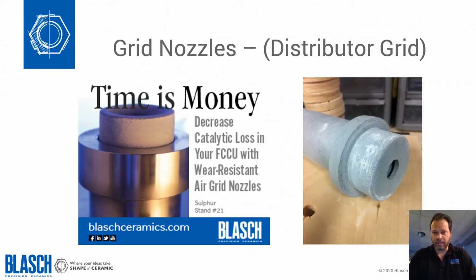In order to facilitate the actual welding of the ceramic nozzle to the lateral pipe, the header, or the plate, you have to incorporate a metallic shroud, if you will, that holds and encases the ceramic. Most of the abrasion is on the inside. And what Blasch does is we mimic the exact orifice size, length, diameter, everything that's existing with the steel nozzle. We do not try to change that. But what we do is we match the ID, we develop a ceramic around that ID, if you will, and then we attach a two-part welded and compressed collar around the perimeter.